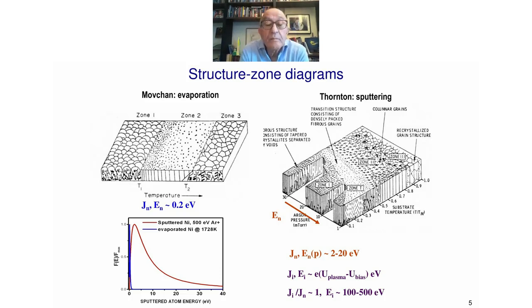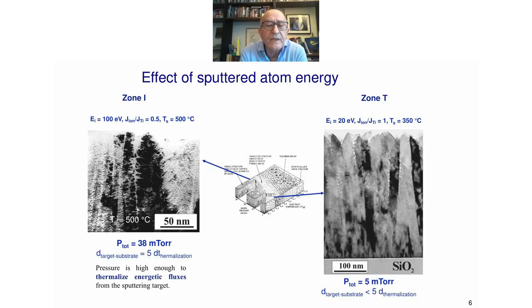So here we can use the pressure to control the energy of the sputtered and backscattered particles in the range of like 2 to 20 eV. And we use also the fact that we have plasma near the substrates to induce ion irradiation. In typical magnetron systems, the ion to metal flux ratio is below 1. And we can vary the energy to some hundreds of eV by controlling the bias voltage. That's the power of bias sputtering that has produced so many coatings over the last, let's say, 50 years, widely spread. Next slide, please.